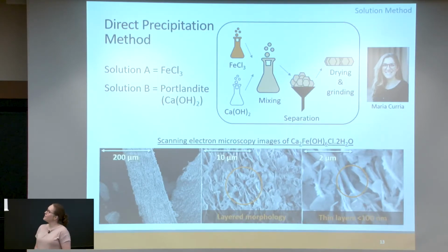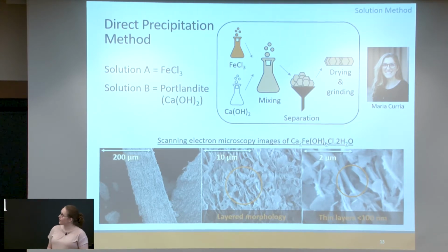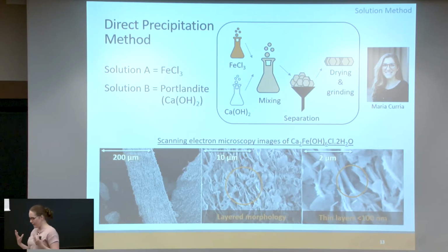So the first method is the direct precipitation method, and this work is done by graduate student Maria Curia. She's come up with this way to make phase-pure calcium-based layered double hydroxide using a solution of iron chloride and a solution of calcium hydroxide, but no sodium hydroxide. Those are mixed together, the system reaches equilibrium, you filter out the solid, and then you can dry and grind it to obtain the material.